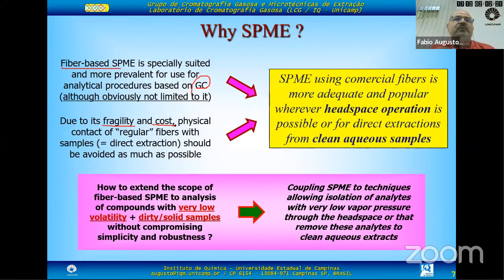So you have to avoid damaging them at all costs because you lose a lot of money if you break a fiber. So we avoid direct extraction, introducing the fiber in the sample. We try to use headspace extraction wherever possible, since most of the species we are going to analyze are analyzable by GC. GC analyzable species are volatile. You can operate through the headspace. Direct extraction, inserting the fiber directly in the sample, is only for clean aqueous samples.